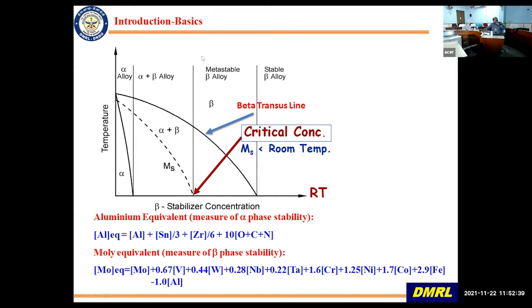Then comes the category of beta alloys, mostly metastable beta alloys, where if you have the alloy and do a beta heat treatment, that is, you heat it up here and then cool it fast enough, then you should be able to retain the beta phase. It does not decompose. That is the classification. Then you can age to attain high strength. So that is, in brief, the classification of conventional titanium alloys. I will talk about intermetallics briefly later on.